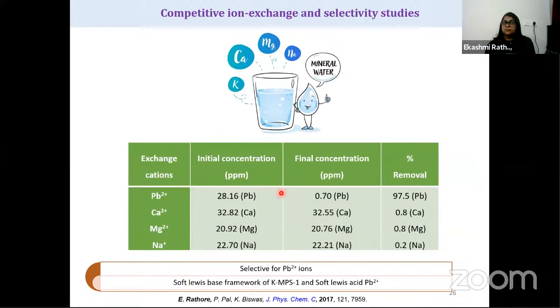We carried out a competitive ion exchange study, and here you can see that we took a similar concentration range of these metal ions, and surprisingly we found out that only lead was getting removed. Here you see that 97.5% of lead was removed. This experiment showed us that it's highly selective towards lead capture, and this selectivity arises from the soft Lewis base framework of KMPS1 and the soft Lewis acid lead.